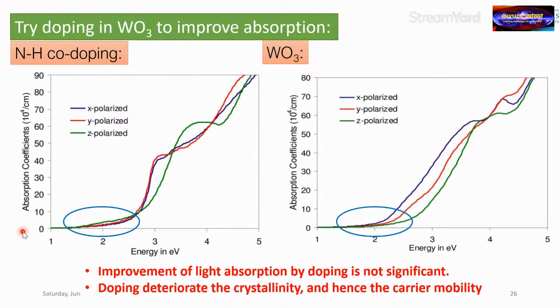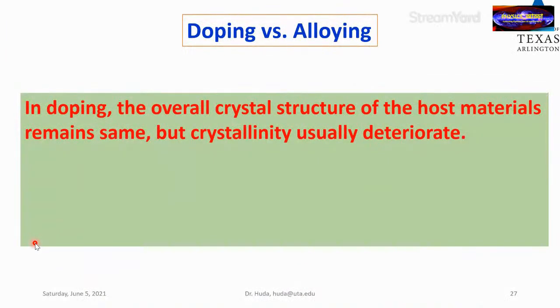So what to do? First of all, the light absorption is not significant enough. Secondly, because there is nitrogen-hydrogen doping, in a real-life experimental scenario it could be more nitrogen than hydrogen, and then there will be some charged impurity state within the band gap, and that can act as an electron trap center. Not only that, usually those kinds of trap centers create strain in the crystal. Hence, the crystalline sample in experiment will have poor crystallinity. Poor crystallinity, in other words, also contributes to high resistivity in the material. Hence, doping, even though it shows some promise, may not be a significant improvement to carry further from here. So what we did after this is to go for the alloy.